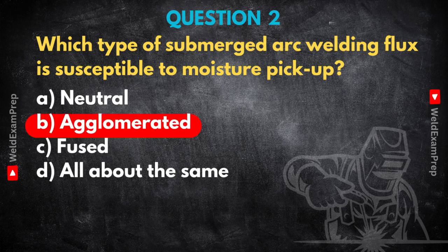Why is that? Well, it's down to how they make them. Agglomerated fluxes mix raw materials with a binder, make pellets, and then bake them, but at fairly low temperatures. And this process leaves them with a kind of porous, granular structure. Think tiny little sponges. So because they're porous, they're really hygroscopic. They just soak up moisture from the air if you're not careful with storage and handling. Unlike fused flux. Exactly. Fused fluxes are different. They melt all the ingredients at really high temps, then crush the glassy stuff that results. It's dense, non-porous, much less likely to grab moisture.